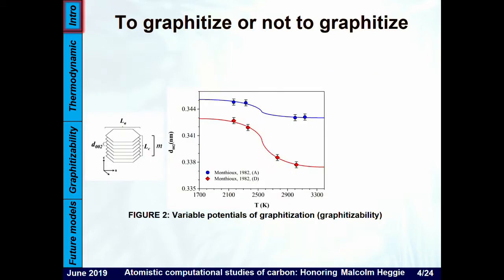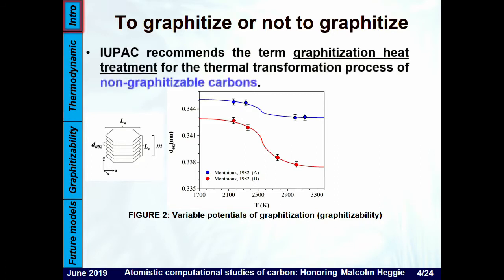So to graphitize or not to graphitize. So to study graphitization, I chose to study the D002 property. So this is the average interlayer spacing of graphenic crystallites. So if you take a carbon material, let's say the red one, and you heat treat it at various temperatures, you will obtain such values, and if you take another carbon material and you heat treat it at these temperatures, you will get these values. So, in terms of the blue values, this is the result of the graphitization heat treatment for non-graphitizable carbon.